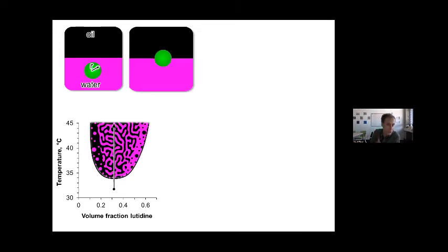This colloid, due to its surface properties, may actually have an affinity for the interface between the oil and the water. And let's assume this particle has a contact angle of 90 degrees and the interface has an interfacial tension. Then in a very simplistic model, you can predict the attachment energy of that particle to the interface with this formula, where you simply have the area that the particle occupies times the interfacial tension between the oil and the water. This very simplistic model neglects effects such as line tension, of course, but it gives us a good intuition first to understand the process.